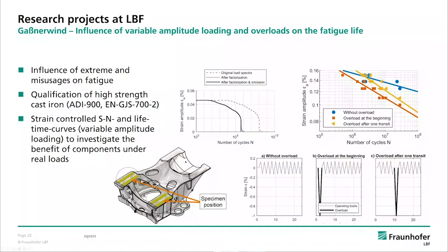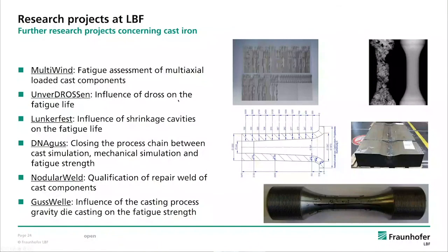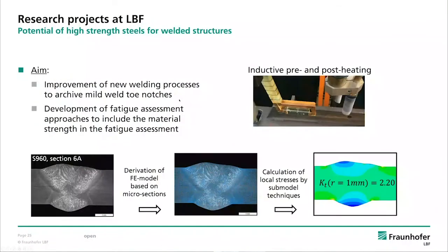There's another important project dealing with variable amplitudes and overloads. We took here specimens out of a machine carrier from a wind energy turbine, and investigated the fatigue behavior with overloads and underloads. And we see here that with overloads that lead to tensile residual stresses, quite low endurable strain amplitudes can be endured. And maybe finally, because I think there might be some questions, I'll go quickly through the slides.